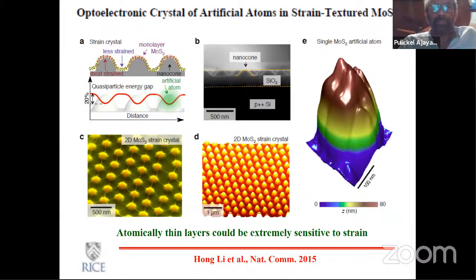Just to emphasize this point, here is some work that we did in collaboration a long time ago, showing that if you wrap around some features that exist on the substrate and then look at the electronic properties, you see significant differences where the strain is concentrated. For example, at the tips of these features, where the molybdenum sulfide is wrapped around, you tend to get more metallic nature of the molybdenum sulfide compared to the typical semiconductor.